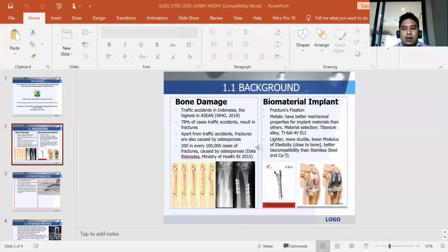The background of my paper is that currently there are still many cracks found in the coating of implant material with hydroxyapatite. This occurs in titanium 64 ELI, extra low interstitial, one of the most widely used titanium alloys for biomedical applications as a load bearing in orthopedic implants.